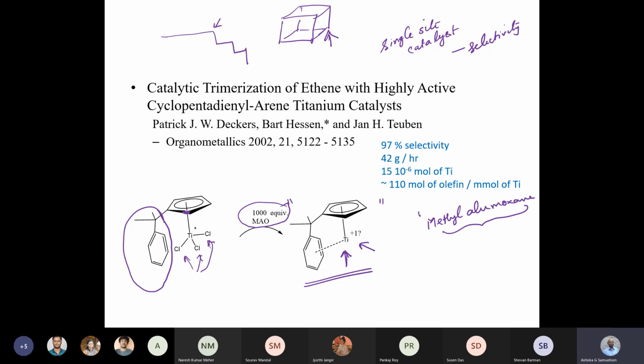But what is this methyl aluminoxane? Like I said, it has got one methyl aluminum, and so this is a repeat unit. So you have another oxygen coordinating to the aluminum. So you have a species something like this, which is polymeric. The ratio of methyl to aluminum is approximately 1:1.